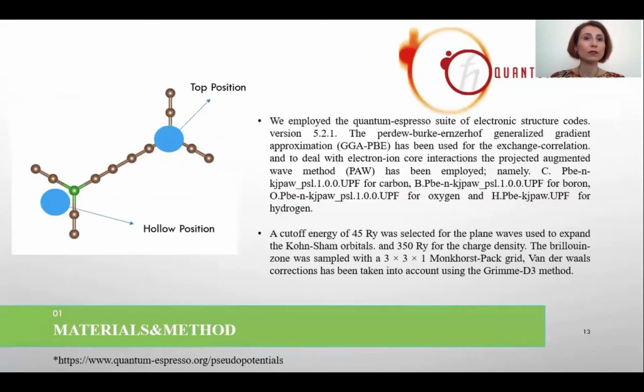We employed Quantum ESPRESSO. The Perdew-Burke-Ernzerhof generalized gradient approximation has been used for the exchange correlation, and to deal with the electron-ion core interaction, the projected augmented wave method has been employed. The cutoff energy value was 45 Ry. The Brillouin zone was sampled with a 3x3x1 grid, and the Grimme D3 method was used for the van der Waals corrections. Hydrogen peroxide is placed on top of the boron and at the hollow position at the hexagonal corner near the boron atoms.